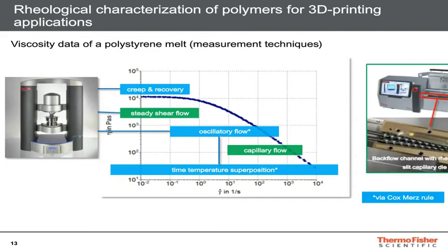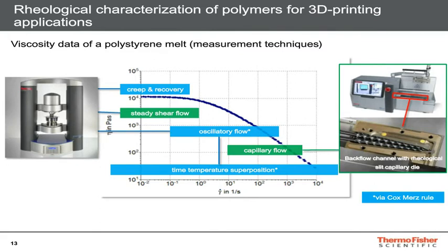However, for most thermoplastic polymers, the widest shear rate range can usually be covered when performing multiple oscillatory frequency sweep tests at different temperatures and utilizing the time-temperature superposition principle, as well as the application of the so-called Cox-Merz rule. And this is exactly how the plot that is shown here was obtained. And as we can see, it includes viscosity data over a very wide measuring range with all the relevant ranges for most technical and processing applications, including FDM.